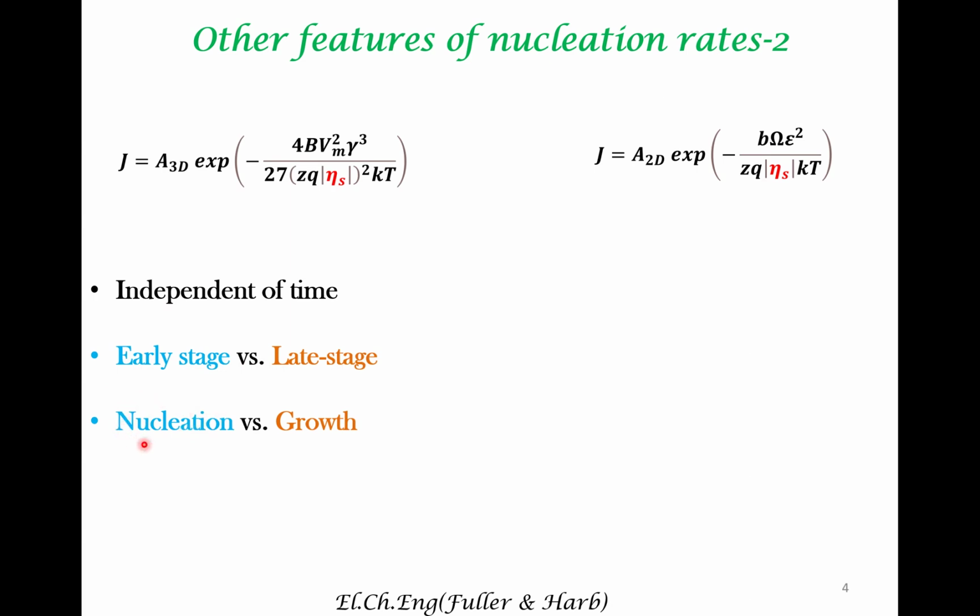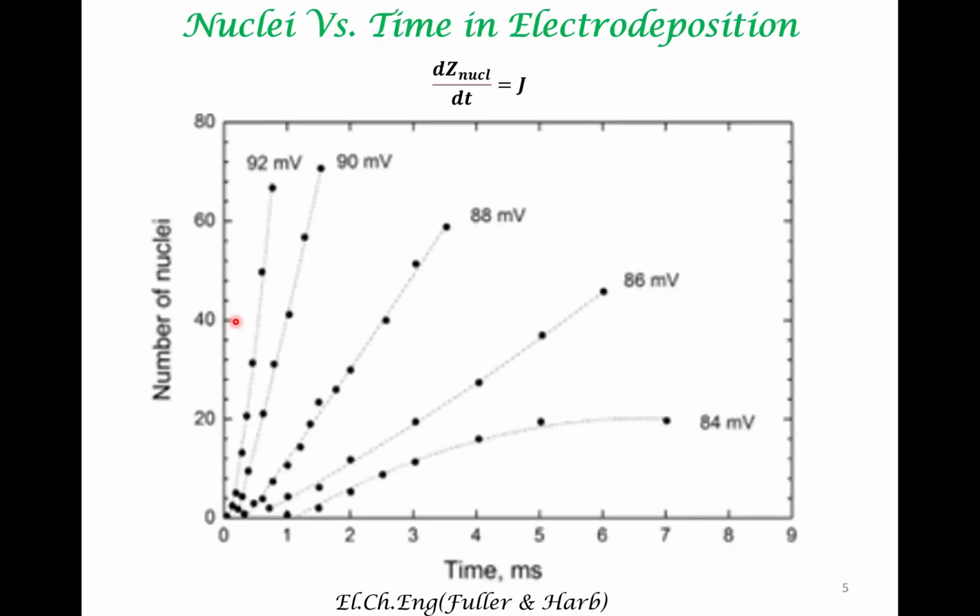But at a later stage of the process, growth dominates. There is perhaps no further nucleation, or at least the nucleation events are much less, and the atoms typically attach to pre-existing nuclei, and then we are focused on the growth of pre-existing nuclei. So in these stages, that the nucleation rate is independent of time is a reasonably good observation.